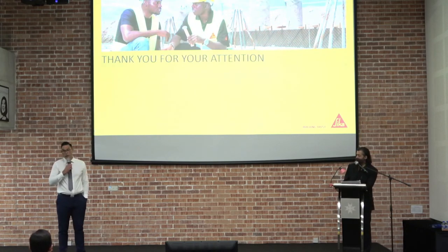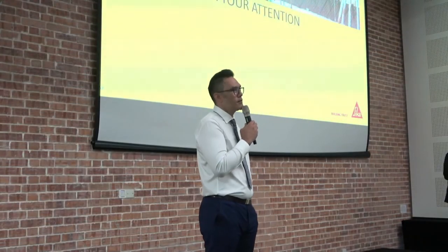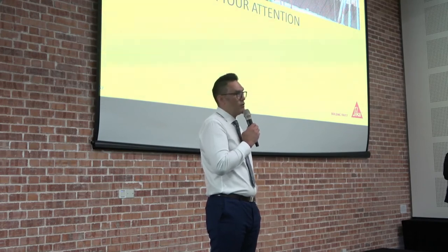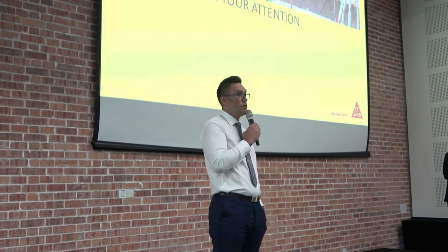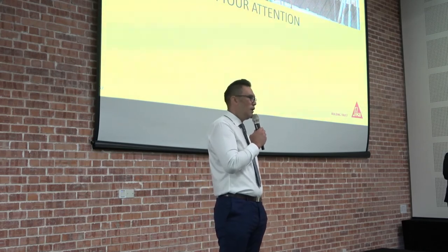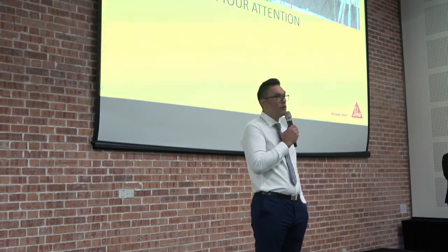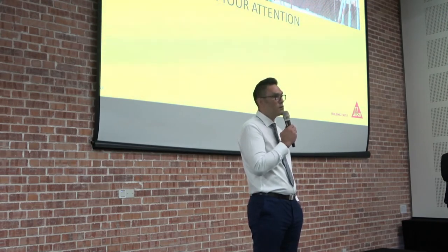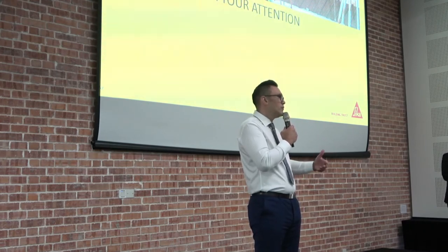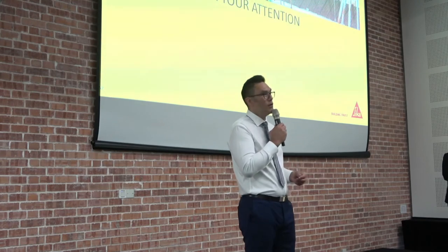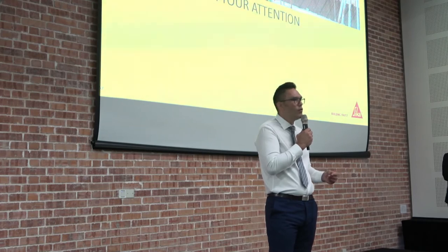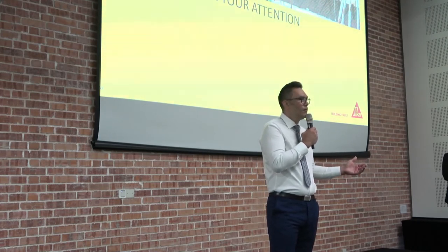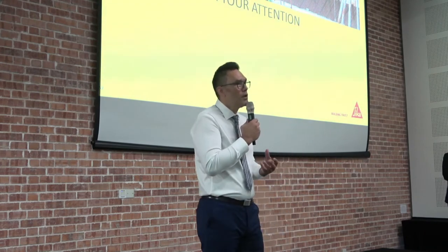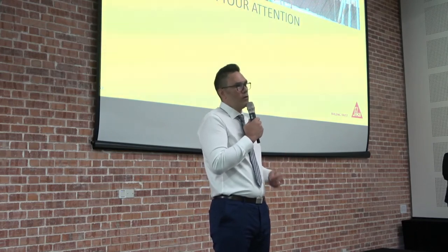A lot. And I'm being straight up here, a lot comes down to the budget. And the performance criteria versus the budget is always going to be a tough ask. Anything near the sea should be protected because of that zone. And you should not really, if you can avoid compromising, try not to compromise on the structure and the performance products when you're in those zones. Equally in the city, we have a lot of CO2, so you have a lot of carbon dioxide attack for your concrete structures. So don't be scared to put in some measures as part of your specification. Say, look, we'd like either a higher performance concrete or some sort of coating to extend the life. Remember, concrete works and it's a great product, but it can also be deteriorated without maintenance or without the right protections in place as well.